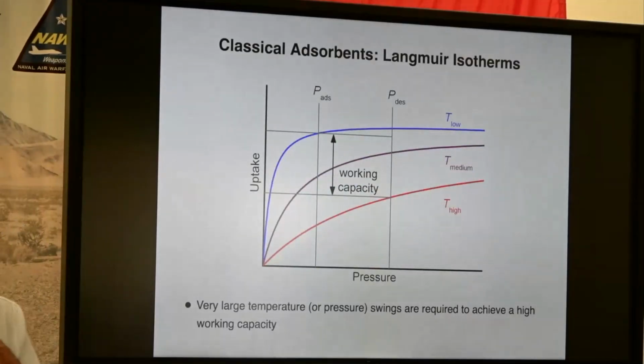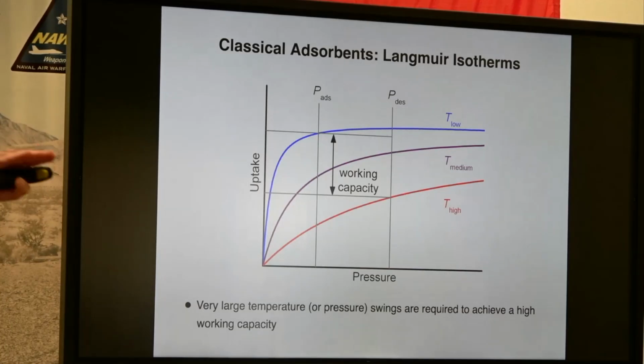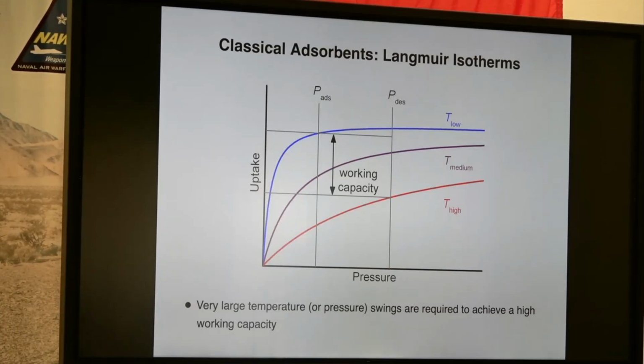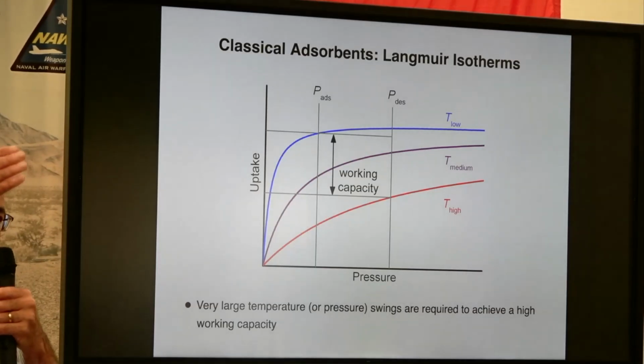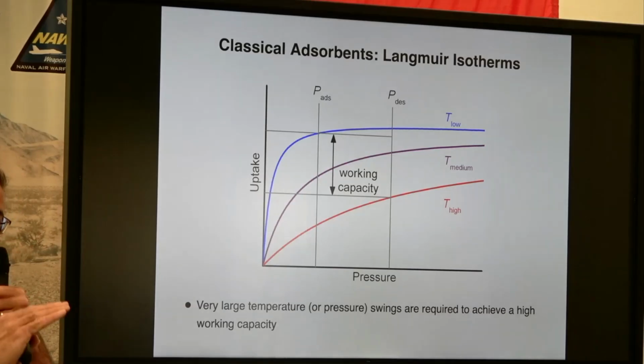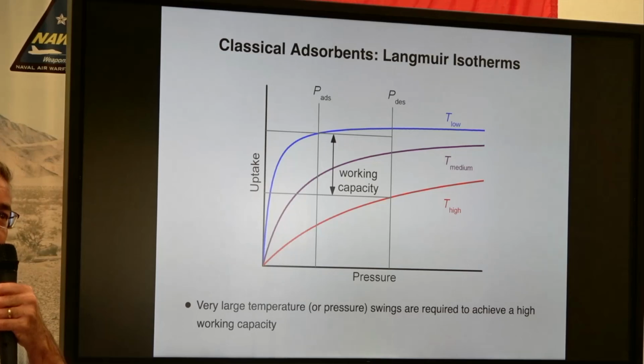And pretty much any porous solid that you would put into that type of bed has this type of response to a gas pressure. This is called a Langmuir adsorption isotherm. Under equilibrium conditions, if you increase the pressure of gas, you'll see a steep uptake and then saturation as you coat the surface. And that isotherm shape is not ideal for an efficient separation because you're going to load up with the molecules at whatever partial pressure they are in your incoming mixture. You're going to adsorb those into your material. And then to desorb, the step where you release the molecules in pure form, you're going to have to either go to very high temperatures, because that Langmuir steep isotherm only gradually loses steepness as you raise the temperature, or very deep vacuum to get the molecules off.